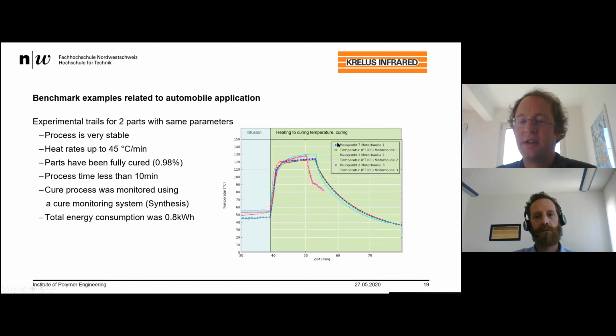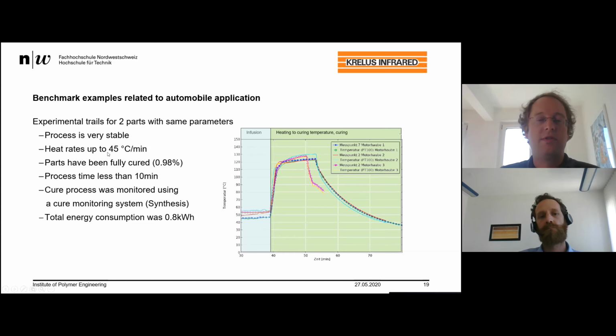And here I am presenting again three different trials. And you can see we varied a little bit with the infusion temperature. And the infusion was really fast and stable, taking around 5 minutes. And then we went up to the curing temperature, and the system reacted really fast. So, we were again able to heat up above 40 degrees per minute. We performed some measurements to check the degree of cure. And here, because we are not going with the temperature as high, we have a really reduced energy consumption as well.